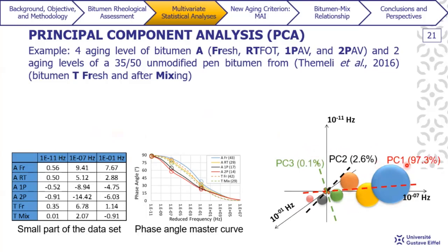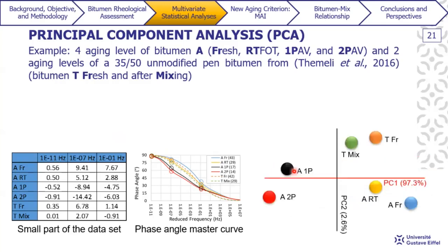So here we have the relevancy of each PC to describe our data set. PC1 in this case accounts for 97.3%, PC2 accounts for 2.6%, and PC3 for only 0.1%. So in this case, we can delete PC3. And instead of having this 3D graph, we can have a 2D graph that is way easier to interpret, with 99.9% of the original data.